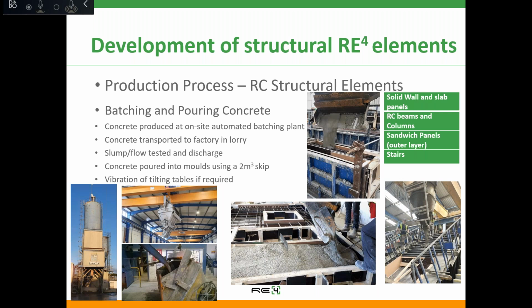There's vibration on the tilting tables if it's required. Usually it is not, because for the horizontal panels and columns and beams, we use the self-compacting mix developed during the RE4 project, and we're happy with that. So we didn't use vibration at all when casting these elements. As you can see in the pictures, the concrete is very flowable.